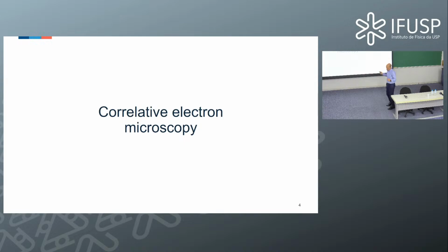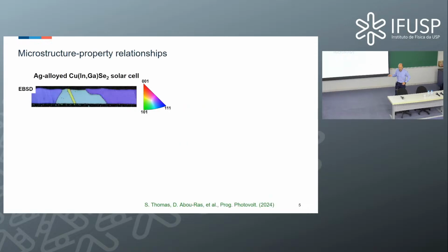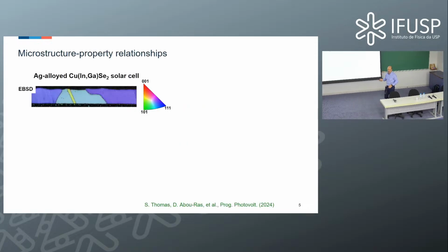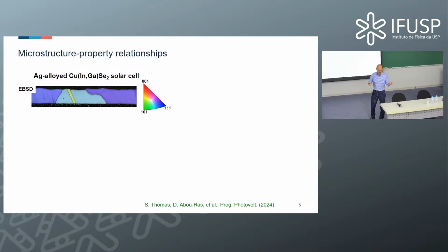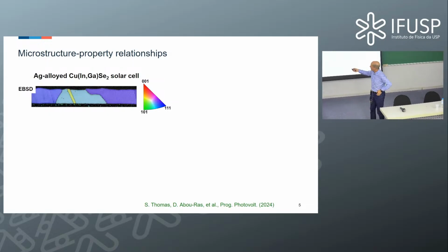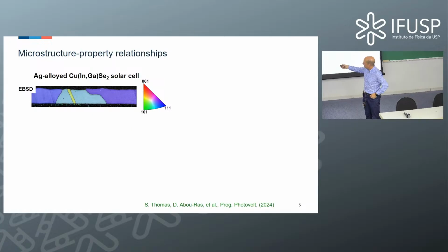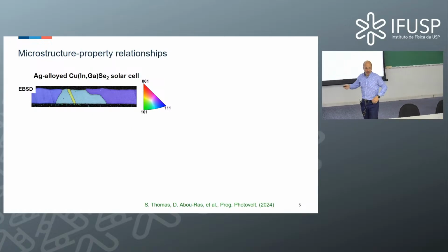Okay, let's go into detail and look at correlative electron microscopy. This is an example of a thin film solar cell. What we look at is a cross-sectional specimen, and this is an EBSD, electron backscatter diffraction map, showing the local orientations in terms of false colors. Basically, what you can do with this technique is to identify individual grains very nicely.